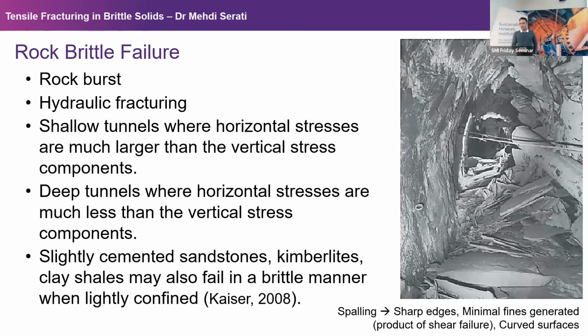The image that you see on the screen is to give you an idea how extreme a spalling incident could be. Imagine you are working in this environment, and these slabs or flakes, which could be very large, up to maybe 1 meter, have sharp edges. The speed varies depending on the stress condition, but in our experiment it could go all the way to 100 meters per second.